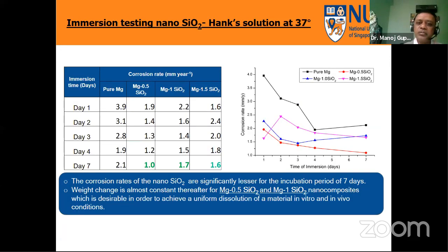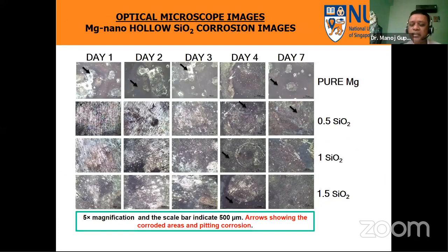For SiO2, the rate of corrosion was marginally higher than HA, but still typically better than pure magnesium. Once again, these materials also show pitting corrosion as the main form of corrosion which degrades the protective layer and affects the corrosion of magnesium.